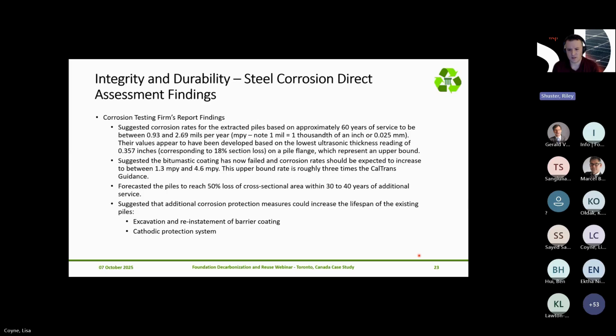So based on this testing, the specialist firm calculated some rates of corrosion for that 60-year service life, and their report suggested anywhere from 0.93 to 2.69 mils per year. It's thousandths of an inch. And it appears that in developing these rates, they used the lowest reading. So from that perspective, this would represent an upper bound, or the most conservative reading of that information. There's also some suggestion that since the coating had failed, they might expect the rates to increase anywhere between 1.3 and 4.6 mils per year. And to put that into context, that highest value there is roughly 3 times the value prescribed by Caltrans for these soils.